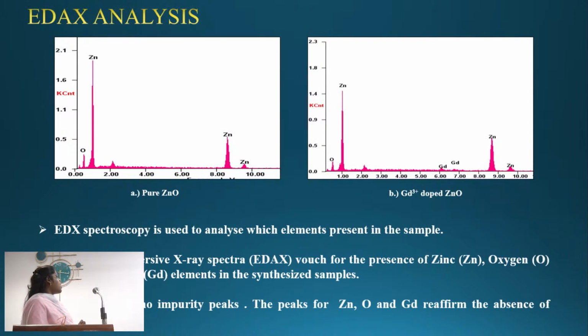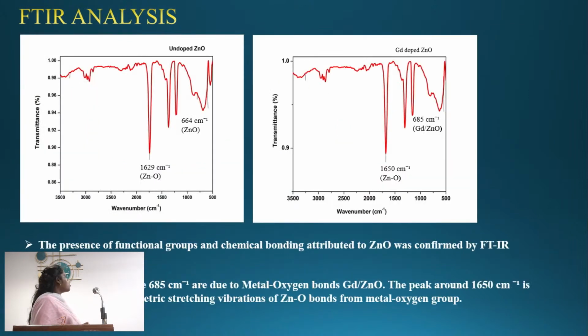EDAX spectroscopy is used to analyze which elements are present in the sample. It clearly shows pure ZnO in the first figure and gadolinium, zinc and oxygen in the second sample. So it's confirmed that my elements are present in the EDAX analysis. The next one is FTIR analysis. The first one is undoped and the second one is gadolinium-doped ZnO. The first one at 664 centimeter inverse is a metal oxygen bond, and for gadolinium-doped, 685 centimeter inverse is a metal oxygen bond, confirming that ZnO and gadolinium-doped ZnO show the metal oxygen bond.